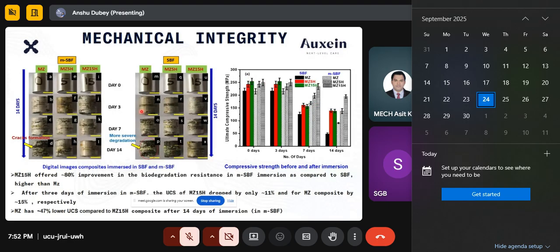This was done in 2 different media, because if you see the bone, we try to mimic the environment of the bone. There are proteins, there are other things involved. So we chose 2 media. One is simulated body fluid, which has all the salts in it, and the other one is modified simulated body fluid, which has proteins inside. We took fetal bovine serum as the protein, which was similar to the bone environment, and we saw the results were better in the case of serum.